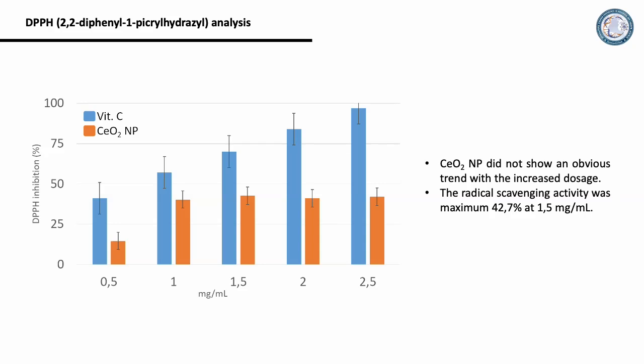DPPH is a dark-colored crystalline powder composed of stable free radical molecules, which is used as an antioxidant assay. The decrease in absorption is considered a measure of the extent of radical scavenging. The radical scavenging activity values were expressed as a ratio, which was evaluated for vitamin C as 98.5% at 2.5 milligrams per milliliter and 42.1% for cerium oxide. But as you can see, cerium oxide nanoparticles did not show an obvious trend with increased dosage. The radical scavenging activity was maximum, 42.7% at 1.5 milligrams per milliliter. We can say it's above 40%.